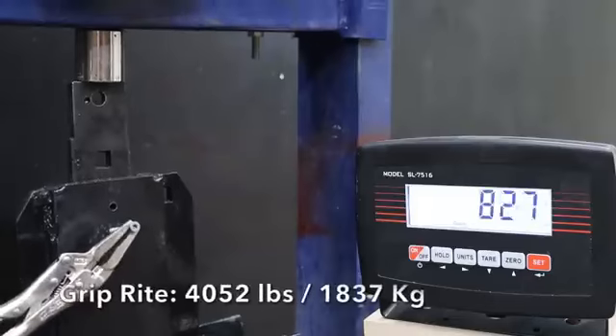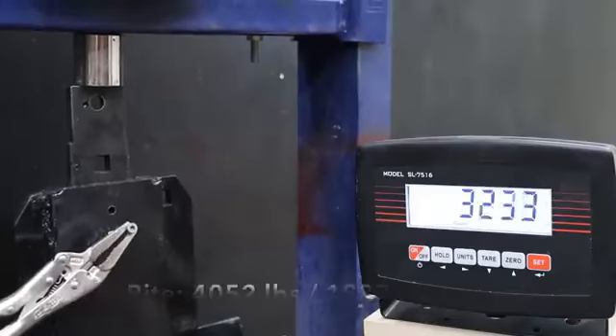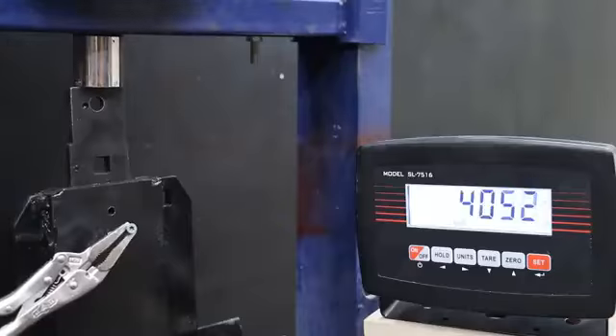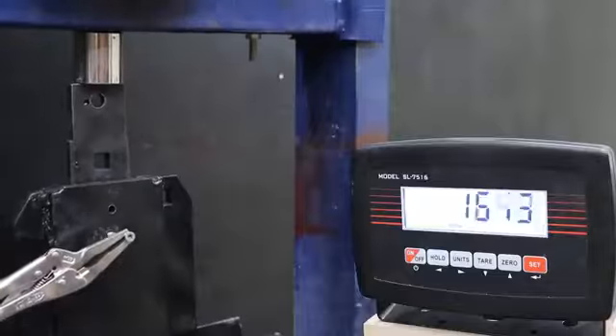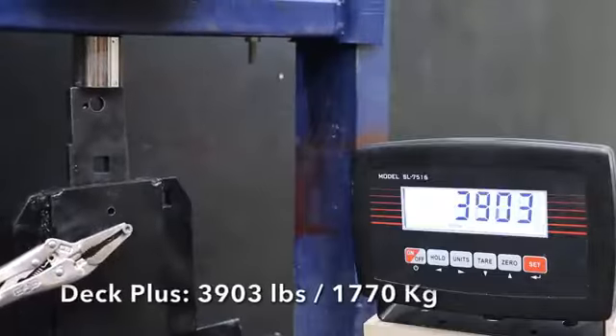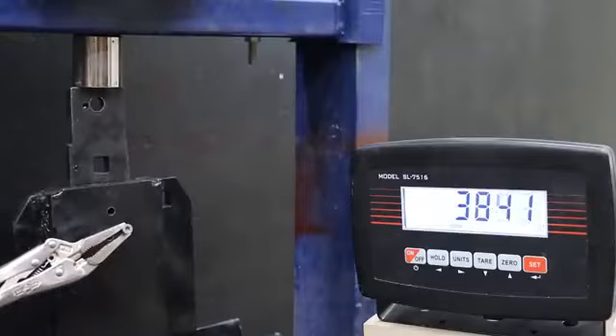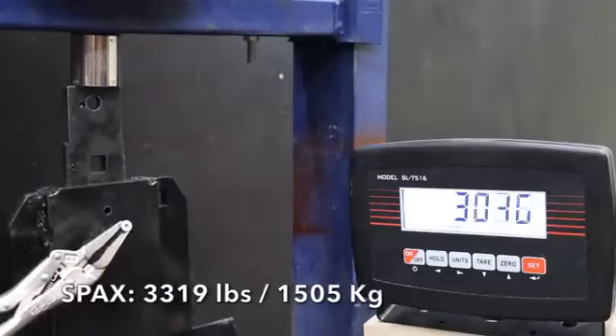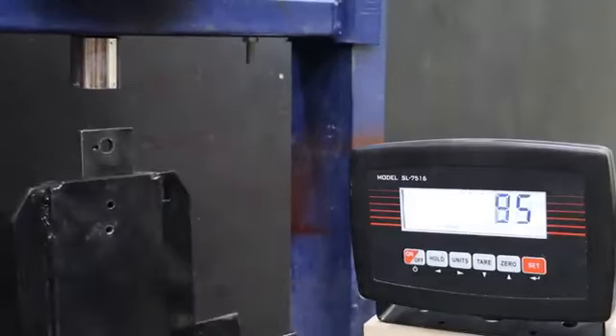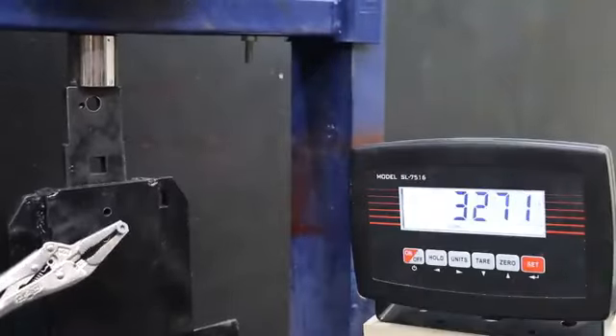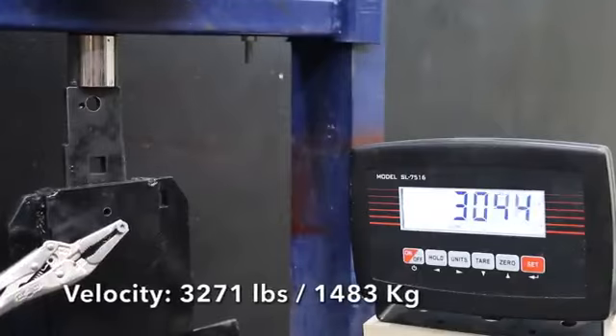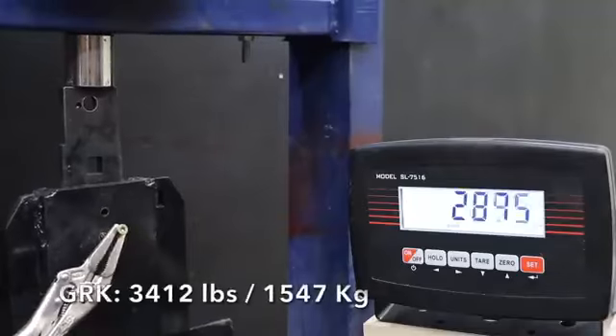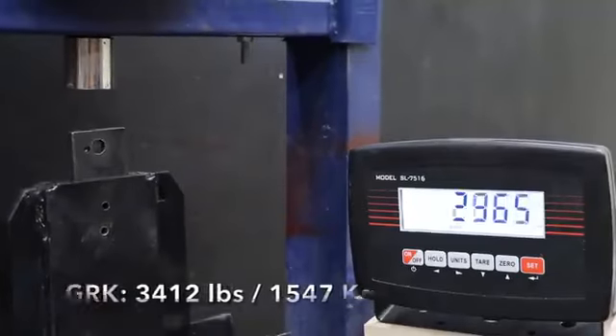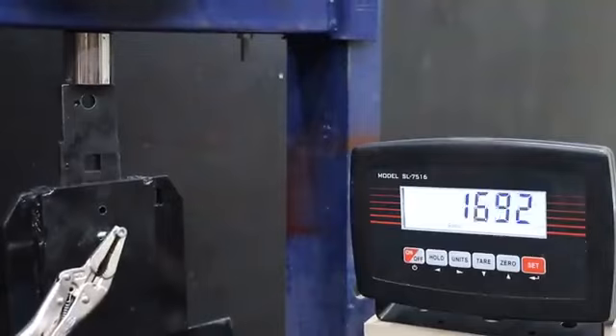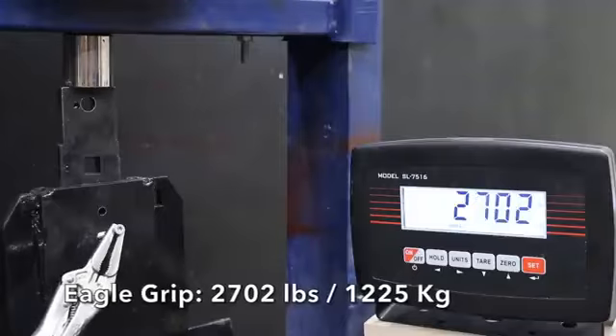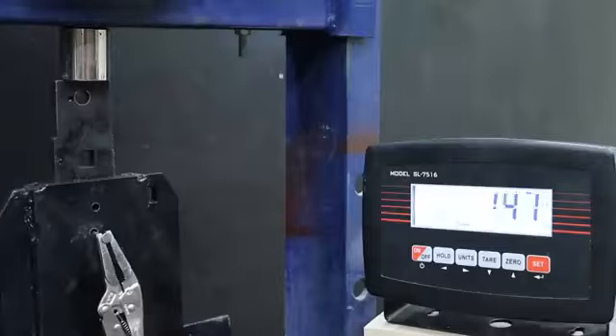The Grip Rite has a larger shaft diameter than most of the other screws, and it moves into the lead at 4,052 pounds. Very impressive. And the Deck Plus performed nearly as well as the Grip Rite at 3,903 pounds and moves into second place behind the Grip Rite. And the SPAX made it to 3,319 pounds before letting go. And the Velocity let go at 3,271 pounds to move into the 5th position behind SPAX. And the GRK made it to 3,412 pounds. And the stainless steel Eagle Claws don't have as much shear strength as some of the other screws at 2,702 pounds. Let's test a 16-penny nail.